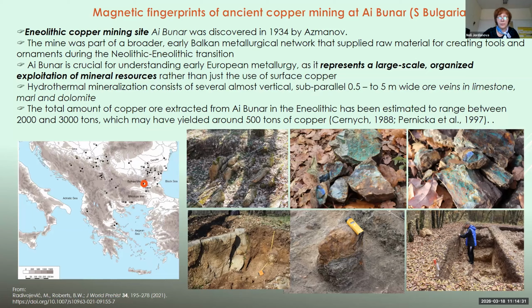And the copper deposit is a result of hydrothermal mineralization, which is found in ore veins in almost vertical subparallel layers of limestone, marls, and dolomite. And archaeological and geochemical research suggests that the total amount of copper which was extracted from the site in Neolithic ranged between 2 to 3,000 tons, which may yield around 500 tons of copper.